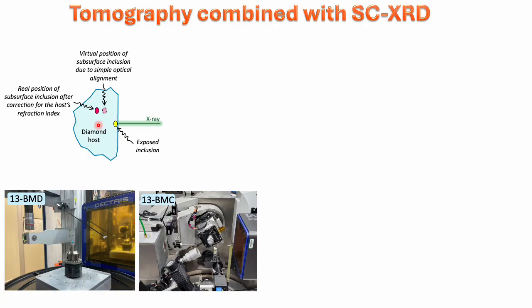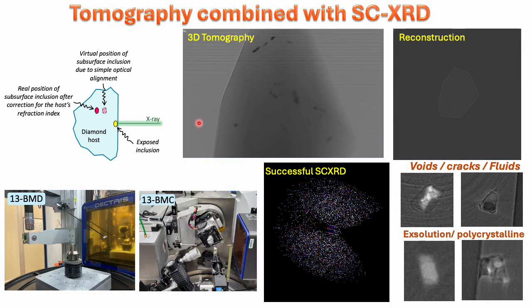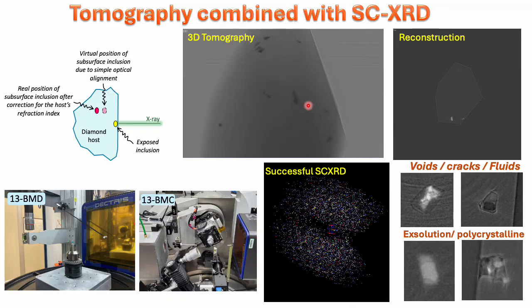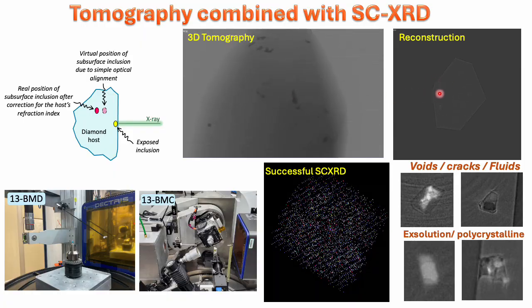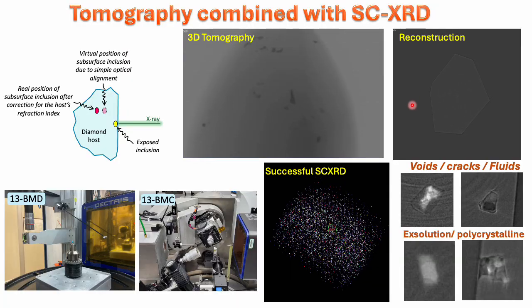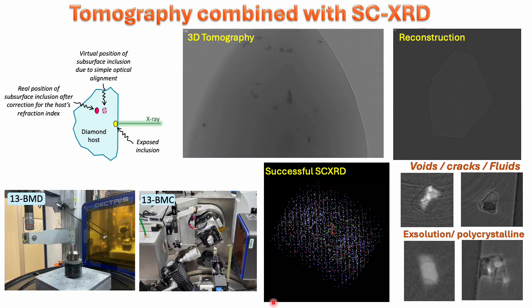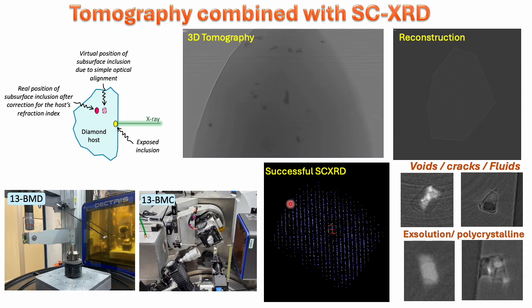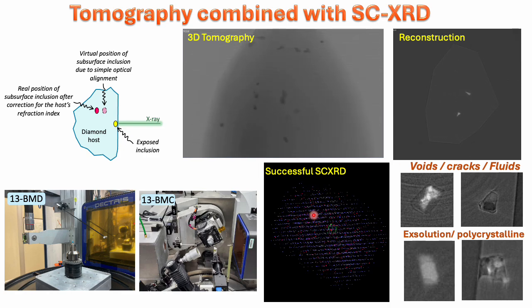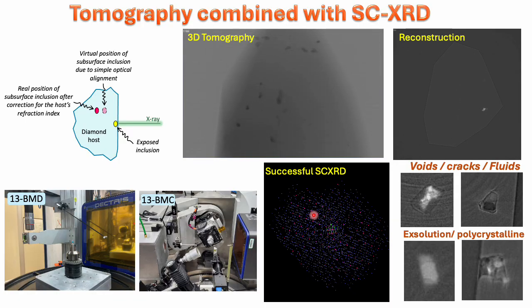When the inclusion is inside the material, we a priori don't know the location to put on the rotation center. So by running 3D tomography, we can reconstruct the entire 3D image of the sample and find the inclusion that we want, bring it to the rotation center, and get very high resolution single crystal data and identify the sample inside the diamond cell without destroying it. That technique is available, and Stella Chariton and Mark Rivers are promoting this technique.